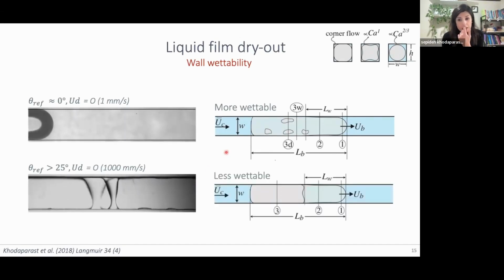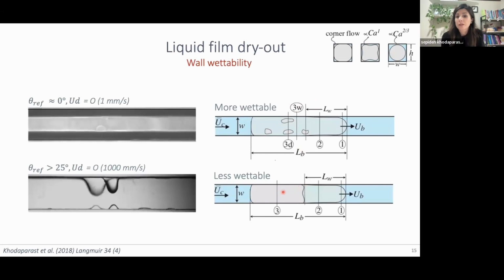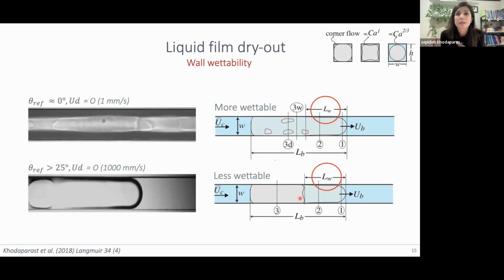So you go from scenarios like the one on the top to scenarios like the one at the bottom. And what we cared about, or at least what we could measure and make sense of, was the region in front of the bubble where the bubble was staying wet. If you think about engineering solutions, so think about microfluidics, microelectronic cooling, you typically use these larger, long bubbles because they increase the mass transfer, and especially they increase the heat transfer because of the thin film that's formed around the bubble.